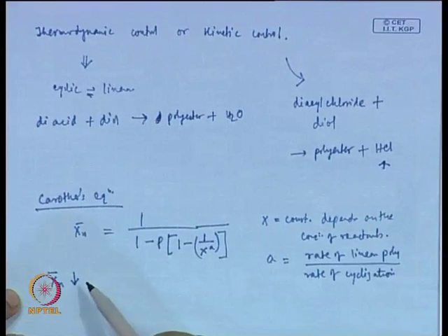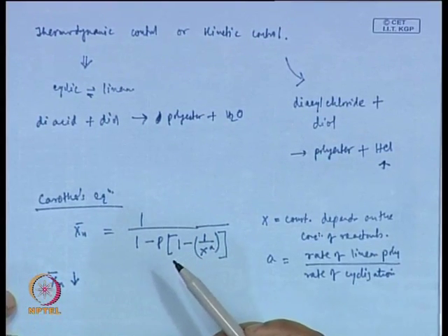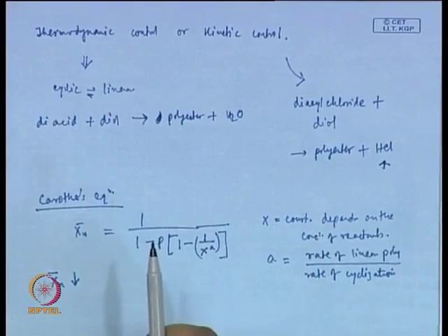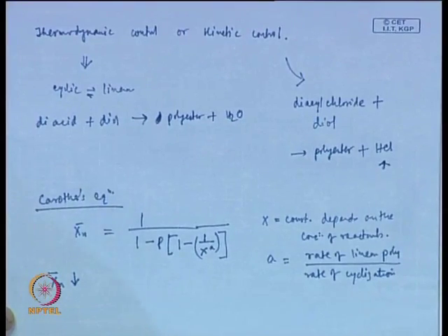So, as more and more cyclization happens, the degree of polymerization also comes down, as we realized in the beginning of this lecture as well. As more small cyclic molecules are formed, it affects both the number average and the weight average degrees of polymerization, but it affects the number average more compared to the weight average degree of polymerization. So, you get the PDI higher than 2.